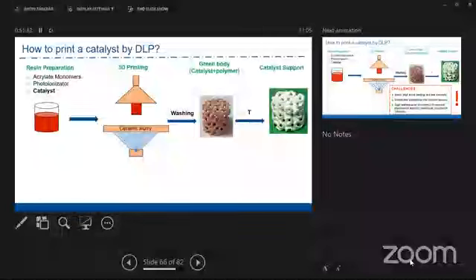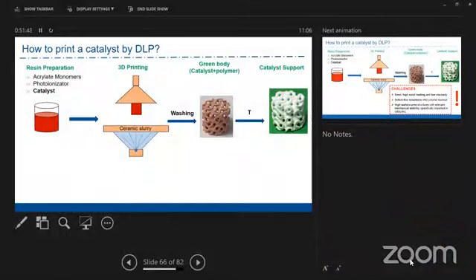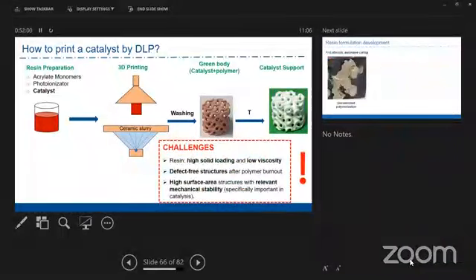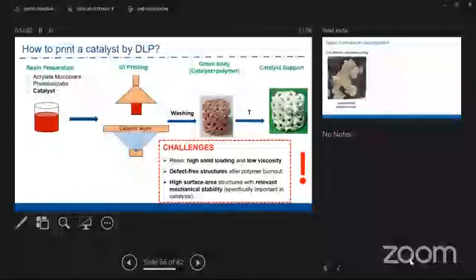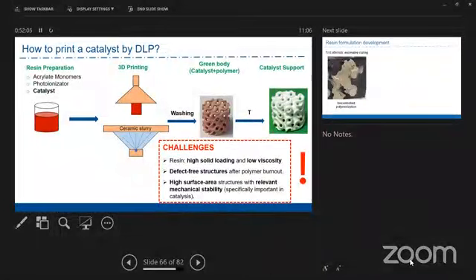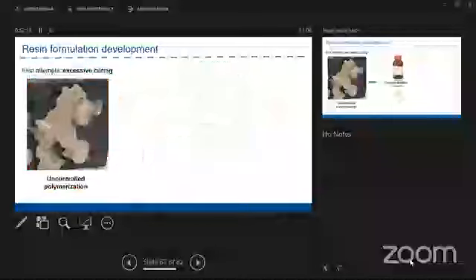And that explains, or highlights, the challenge. If we have too low concentration of this monomer, too much of ceramics, then we are not able to print. And if we have too high concentration of the resin and very little of the ceramic, then after calcination, the body will not be mechanically stable. So it took approximately 1 year to come to some sort of a recipe to make this alumina. We started with alumina. Now we also are able to print zeolites.